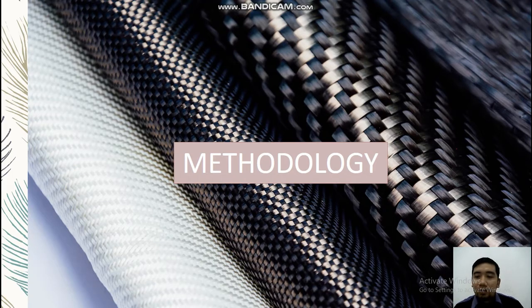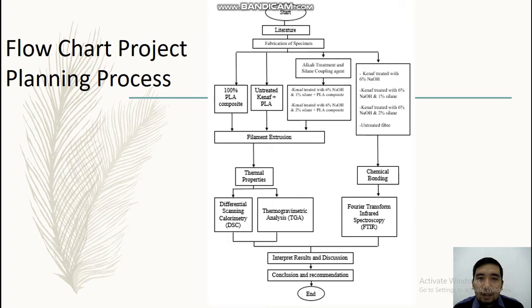For methodology, we can see my process starts with fabricating the specimen. For my project, I use 4 samples: 100% PLA, untreated Kenaf fiber with PLA, Kenaf treated with 6% NaOH and 1% silane with PLA composite, and the last one is Kenaf treated with 6% NaOH and 2% silane with PLA composite.